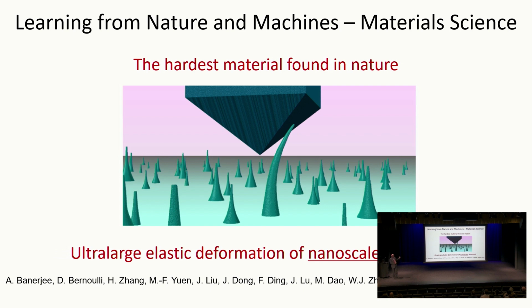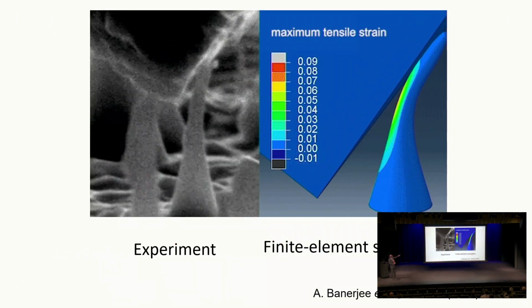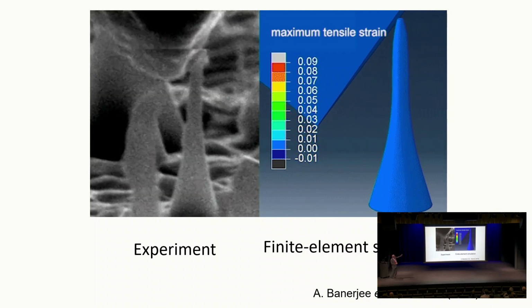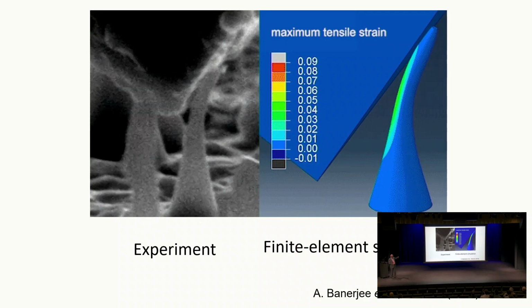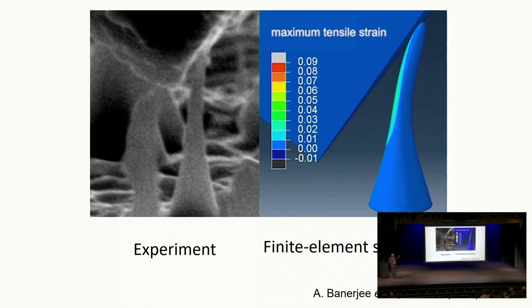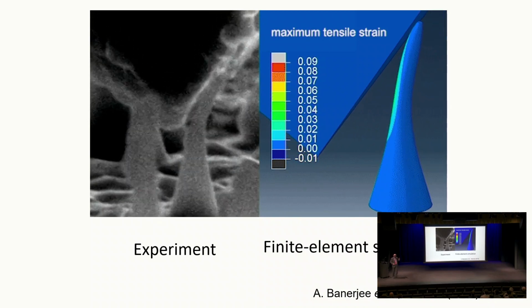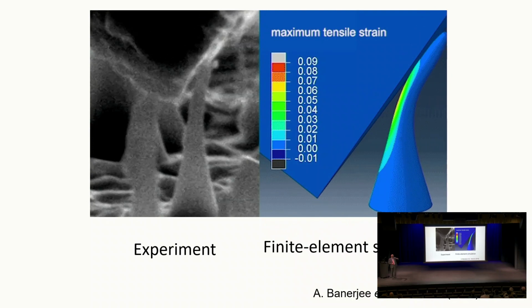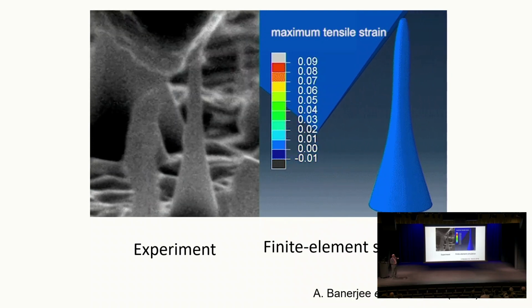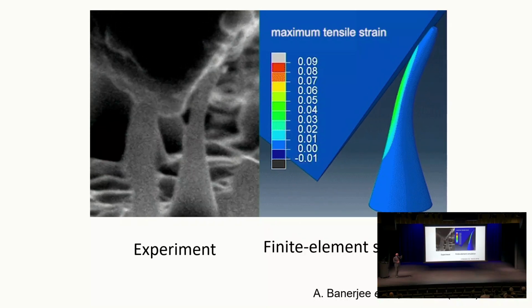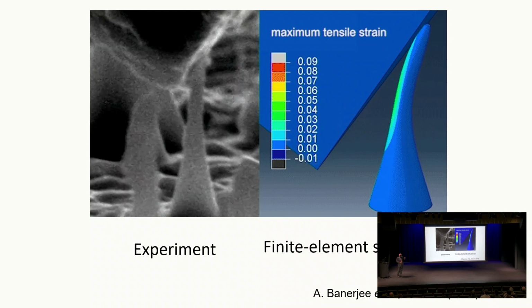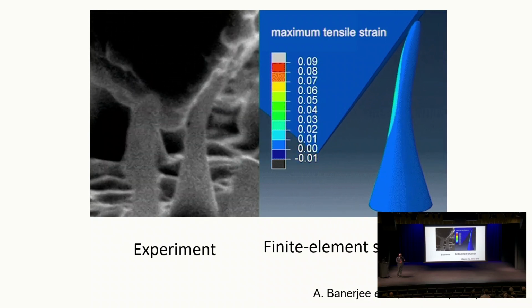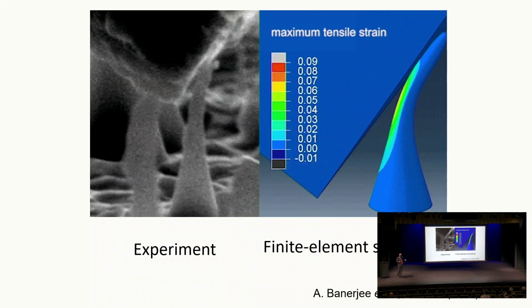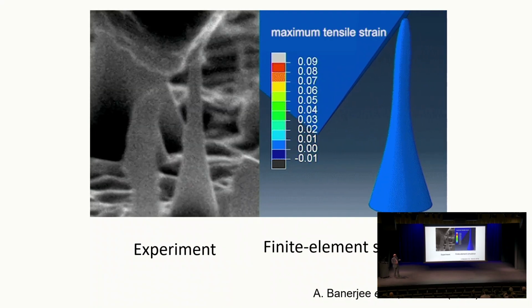Diamond can be single crystal or polycrystal, and we did both. The first video that you're going to see is single crystal diamond, and the simulation is for exactly the properties of single crystal diamond for the same crystal orientation. So you can see on the left, the diamond indenter comes and pushes, and then when it retracts, the needle turns back. Needle goes back. On the right-hand side, it's a finite element simulation, and the color contours are on the tensile side of the bent specimen. You have the maximum tensile strain, and what you find is that the maximum tensile strain is as high as 9% before it breaks. 9% strain in diamond at room temperature, and pretty much ambient conditions, but in a vacuum environment.